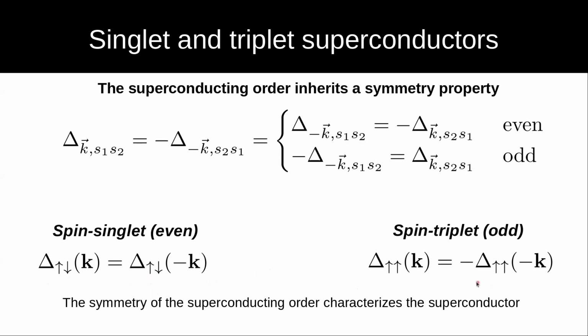And then there's the other case of unconventional superconductors, which is spin triplet superconducting order, in which if you change the sign of k, you essentially pick a minus sign on your superconducting order. And this symmetry property is essentially what allows you to characterize your superconductor. And this symmetry property has massive consequences. For example, this type of superconductor that you see on the left, spin singlet superconductor, is not sensitive to local non-magnetic disorder. Whereas this superconductor that you have on the right is very sensitive to non-magnetic disorder. So if you have a material and you see that it's superconducting, but that it is very sensitive to having non-magnetic impurities, then you know that probably it is going to be some odd superconducting state and perhaps a spin triplet.